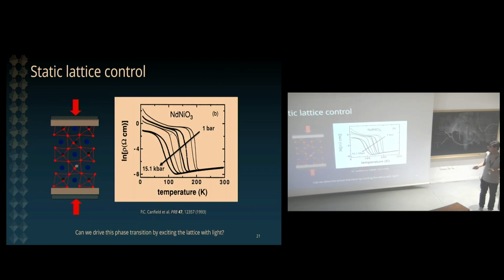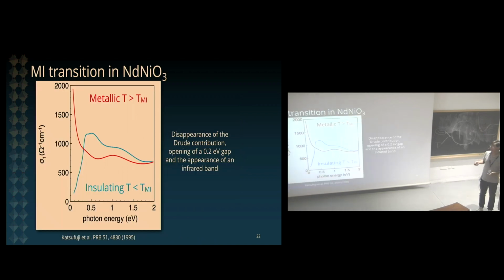So it's been known for a long time that if you can squeeze your material, if you can apply hydrostatic pressure or epitaxial strain or other forms of lattice control, you can strongly affect this metal to insulator transition. So there's this nice experiment from the 90s where they were applying pressure to neodymium nickelate and widely tuning the transition temperature. So the question is, can we now do this interesting lattice excitation and observe some changes in the properties of neodymium nickelate?